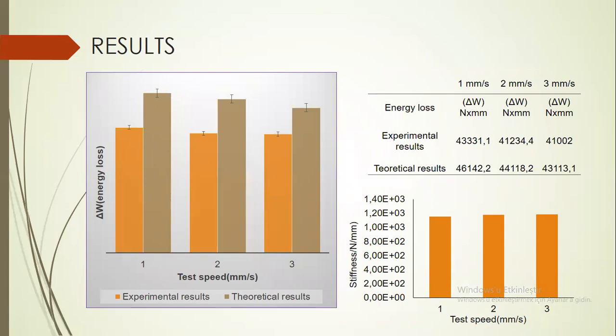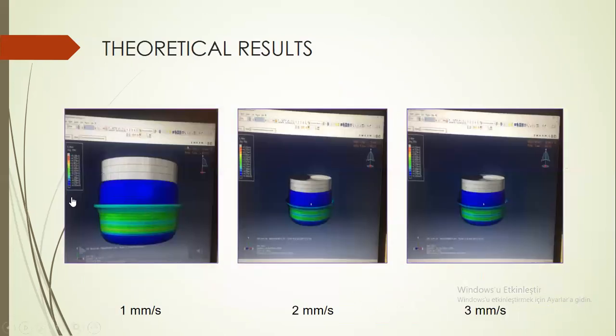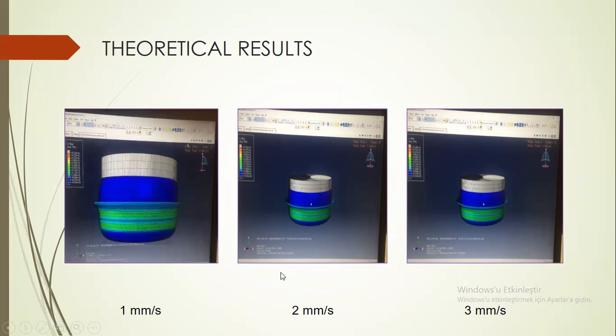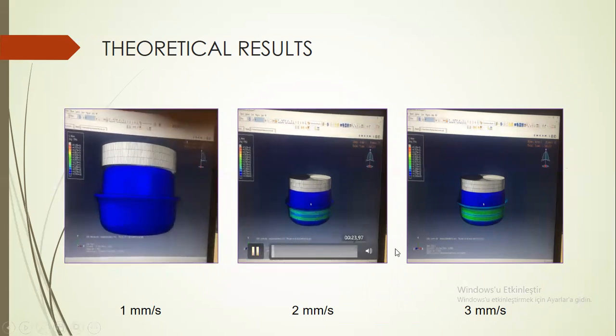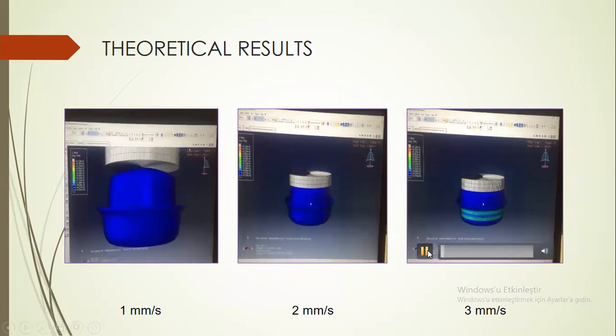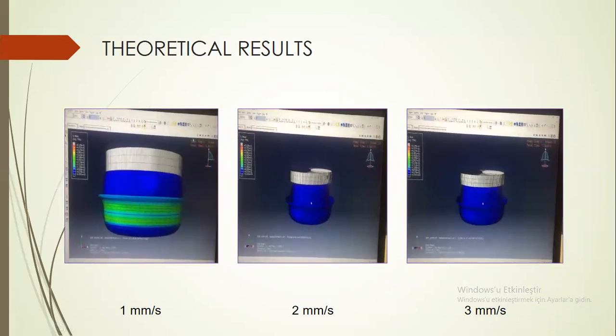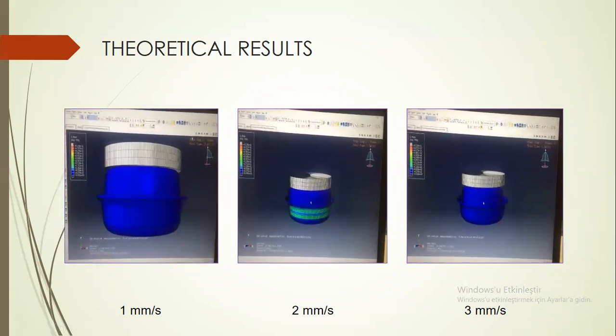The content of rubber materials is different from other materials. It's affected by many variables. Therefore, in nonlinear analysis, there is a certain deviation, approximately 7%, in the correlation between test results and analyzed results. You will see here finite element analysis at the 1 to 3 millimeters per second.